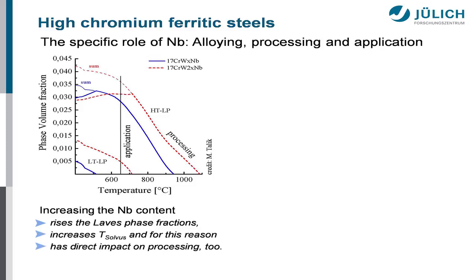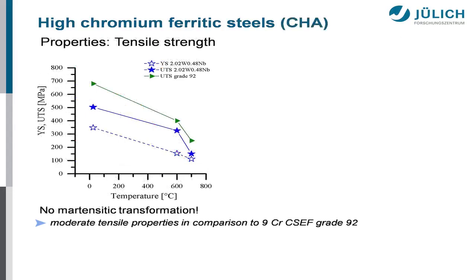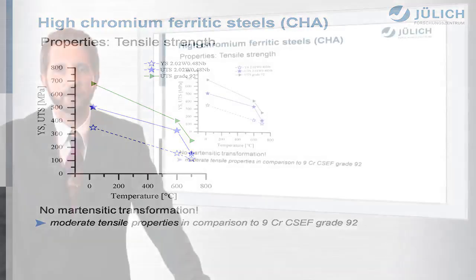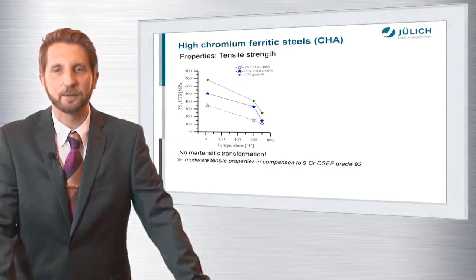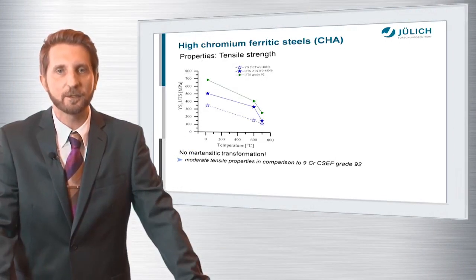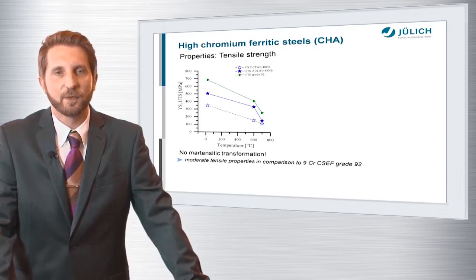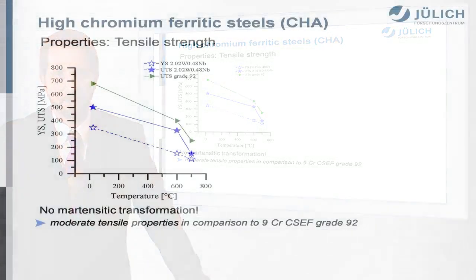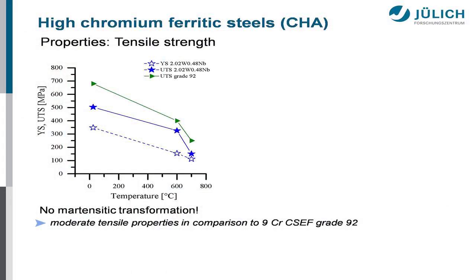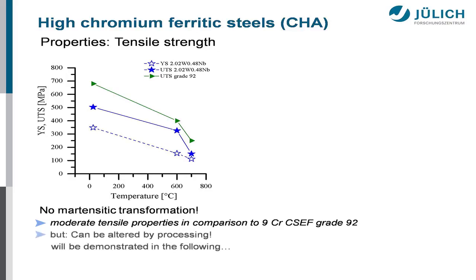So now coming to the properties, starting out with mechanical properties, the tensile strength. As I already pointed out, our materials are fully ferritic. We do not have martensitic transformation, and that's the reason why we do only reach moderate tensile properties in comparison to a 9 chrome steel, here grade 9-2, which is represented by the green curve, the green triangles. The filled blue stars represent a chemical composition quite close to the commercial Crofer 22H alloy, and you can see it's far below, but this is not really a problem because we can alter the tensile properties just by processing, and this is what I'm going to demonstrate to you in the following.